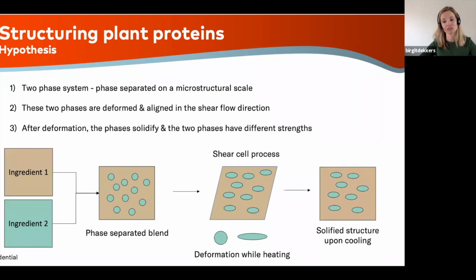One of the things that we found during our research is that you often use a two-phase system, which is phase separated on a microstructural scale. So if you blend two ingredients, it can be proteins, it can also be proteins and polysaccharides, for example, soy, or so in the case of soy protein concentrate, you have the proteins and the polysaccharides in there, and these two are phase separated on a microstructural scale. What we then do in the shear cell process, we are deforming and aligning these types of ingredients in the shear flow direction. Upon cooling, after deformation, the two phases solidify, and these two phases have a different strength. And that's the whole basis of creating fibrous structures.